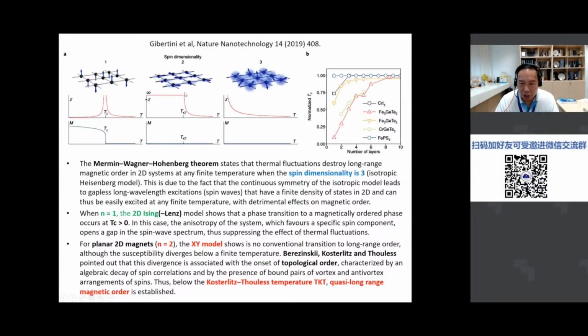It shows no conventional transition to long-range order, but Berezinskii, Kosterlitz, and Thouless, these are Nobel laureates for topological phases, pointed out that you can get this kind of divergence at a particular temperature with the onset of topological order. And it's characterized by the decay of spin correlations and the presence of bound pairs of vortex and anti-vortex arrangements. So this Kosterlitz-Thouless temperature, TKT, below it, quasi-long-range magnetic order is established. So you can sort of achieve magnetism in such a system.